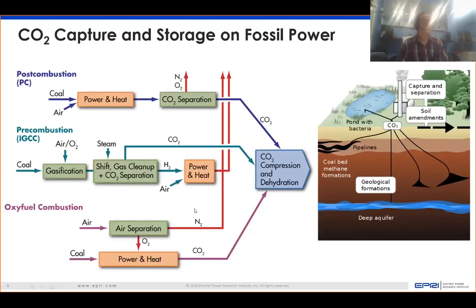So what exactly is CO2 capture and storage on fossil power? I won't spend much time on this slide because I assume most people are familiar with at least post-combustion, in which you take coal and or any kind of fossil fuel, and you do a separation of CO2 from predominantly nitrogen, and then the CO2 is separated and you can compress and dehydrate it. You can also do pre-combustion capture, in which you do gasification followed by water gas shift and do a CO2 hydrogen separation to get out CO2.